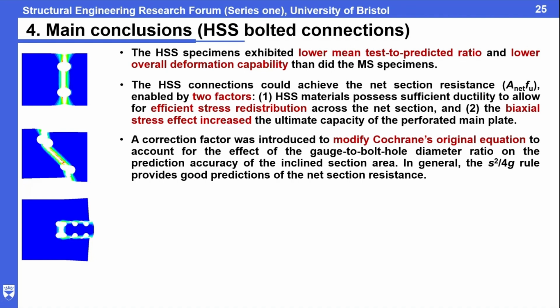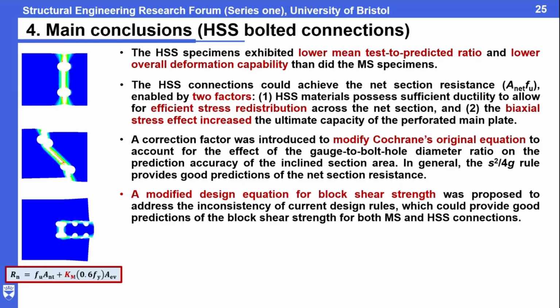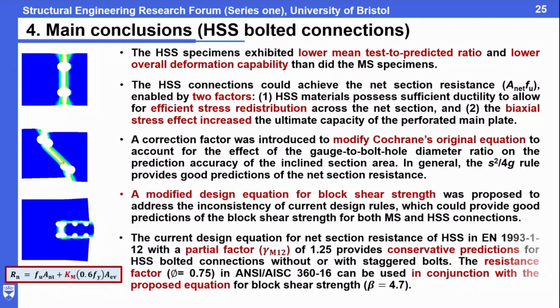Then we go to the s²/4g rule, the background. We revisit it and propose a modification factor to account for the effect from G over D0. And for the block shear strength, we modify the design equation to have a consistent one. The last is the reliability analysis to check whether the partial factor or safety factor can still be used for the high strength steel. So for the bolted connection of the high strength steel, we follow a similar standard procedure: test, numerical, then theoretical, and then combined with reliability.